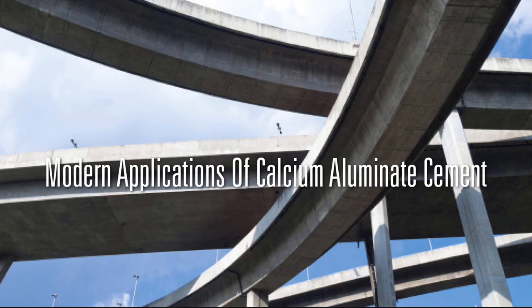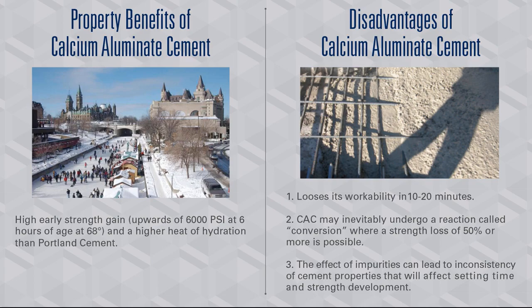And then today you see it in bridge and road construction. When they need a very high PSI strength and lower temperatures, it's normally when we're seeing the use of calcium aluminate cement. So high early strength gain with this material. We have upwards of 6,000 PSI within 6 hours at 68 degrees. Higher heat of hydration than you would with Portland cement.